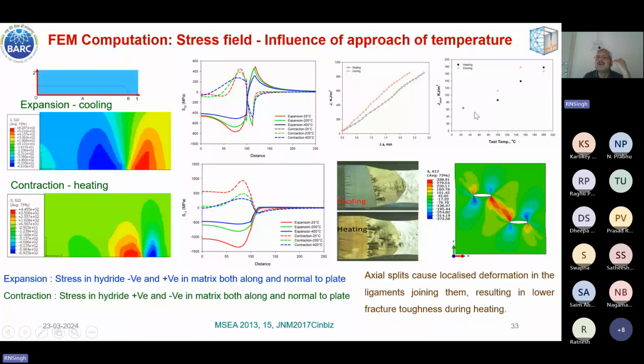At lower shelf and upper shelf, the difference is not much, but in the transition regime, both heating and cooling is having some effect on fracture toughness. You see the fractograph also in case of cooling, what is happening is that number of axial splits on the fracture surface is very low. In fact, these lines you are seeing, they are called axial splits. They are because of circumferential hydrides. Because of axial split of a stress, these circumferential hydrides cleave apart and they give features like axial splits. But in case of cooling case, you see number of axial splits are much lower.